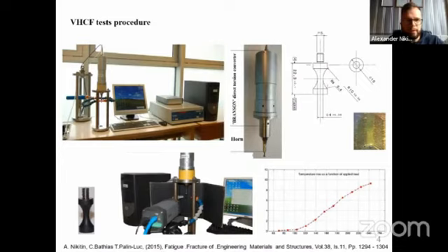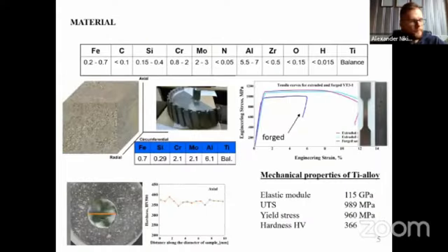Here you have a setup for the torsional test. Right now we use a direct pure torsional system presented on the slide. We are sure that our loading condition is good, because we are working at low temperature with constant amplitude loading, and we can perform a perfect calibration with a strain gauge presented on the right. Based on the procedure that we developed for torsion tests, we performed very high cycle fatigue tests at 20 kHz in pure torsion for a titanium alloy. The details of the titanium alloy are presented here.